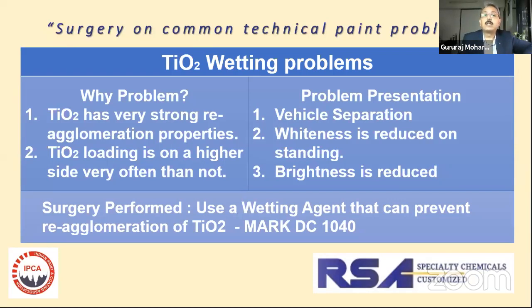But why are we talking about it? Titanium has one basic property which no other pigment has, and that is re-agglomeration or reflocculation properties. You have dispersed your titanium, you have ground it well, but what happens over a period of time is titanium particles reflocculate and they come out of the system. Say, for example, you have added 25% titanium in your enamels and made a very nice white, ultra white or bright white, as many people call it. But after 3 months, the titanium particles reflocculate, reagglomerate, and the effective dose of titanium might be 16 to 18%. Rest of it has hidden behind each other because of the flocculation.